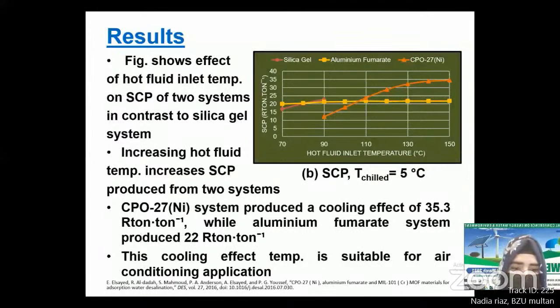The figure shows the effect of the hot fluid inlet temperatures on specific cooling power of two systems compared to a silica gel system. The figure shows that increasing the hot fluid temperature will increase the SCP produced from the two systems. The CPO-27 nickel system produced a cooling effect of 35.3 refrigeration tons per ton, while the aluminum fumarate system produced 22 tons of refrigeration per ton. Hence, it can be concluded that the cooling effect temperature is suitable for air conditioning applications.